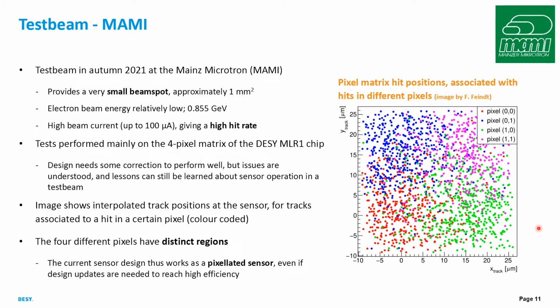So we went to Mainz to do a test beam at MAMI, the Mainz Microtron, which is called MAMI. And the MAMI facility provides a very small beam spot, which is nice. It has a relatively low electron beam energy though, at 0.855 GeV, but a high beam current, which gives a high hit rate. And we need this because our pixels are so small, but then we've also found some inefficiencies in our pixel matrix, which means we're efficient in rather a small region.